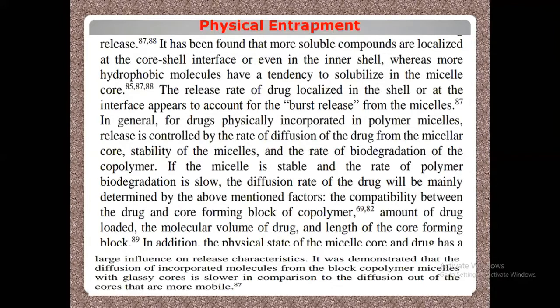In addition, the physical state of the micelle core and the drug has a large influence on release characteristics. It was demonstrated that the diffusion of incorporated molecules from block copolymer micelles with glassy cores is slower in comparison to the diffusion out of cores that are more mobile to the molecules.